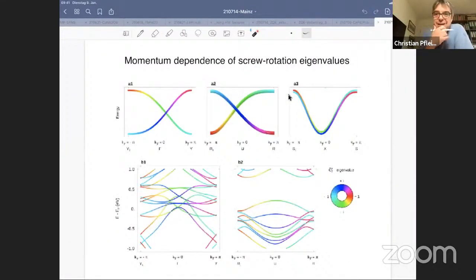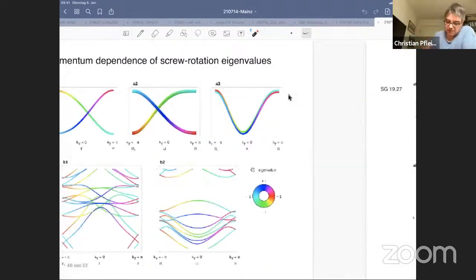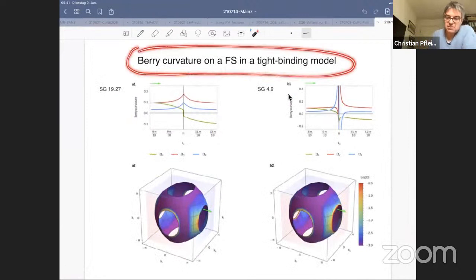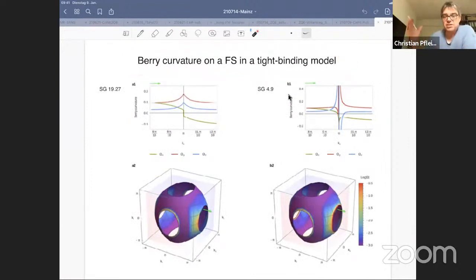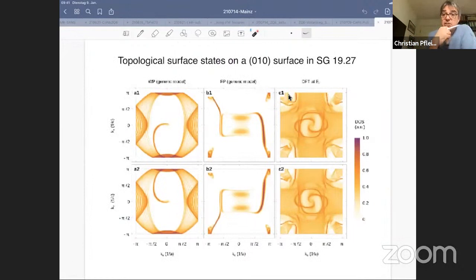I'm really running out of time, so I'm sad to say that I have to skip the theory slides. Of course, Andreas and they did these calculations of these eigenvalues, to see how the orbits connect. They also calculated the Berry curvatures at the Fermi surface, right? And we see that a lot of the Berry curvature is basically pinned to the Fermi surface, exactly where the nodal planes cut. And finally, you expect Fermi arcs due to these nodal planes when you apply a field and suppress them in a certain direction. This is not the case. I showed one example for cobalt silicon when you have them on all three faces.